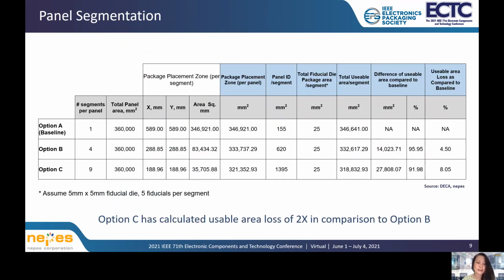Let's take a look at panel segmentation on the 600 mm panel. In general, a 600 mm square panel can accommodate upwards of 5 200 mm wafers. Some considerations to take into account for maximizing gross die per panel are segmenting the panel into 9 200 mm squares or 4 300 mm squares for backend processing. Our goal here is to minimize costs of manufacturing as much as possible to ensure backend tools such as testers, backgrind, saw, ball drop process, or laser marking are fungible with wafer level CSP production in the factory.